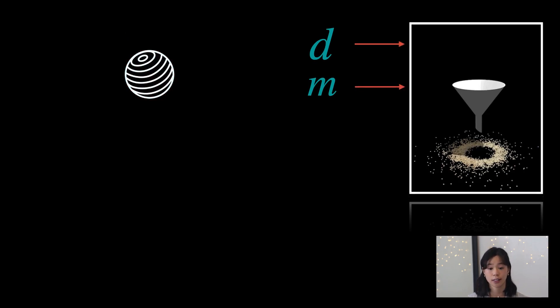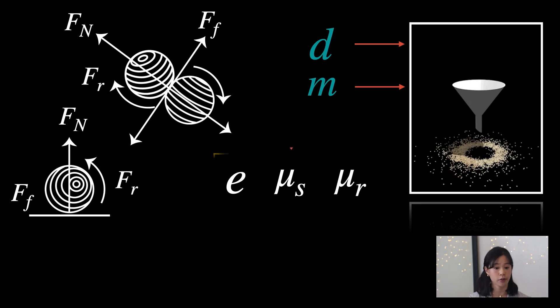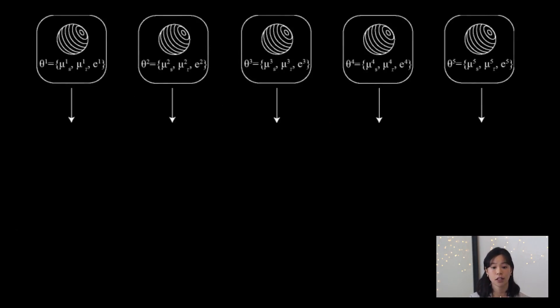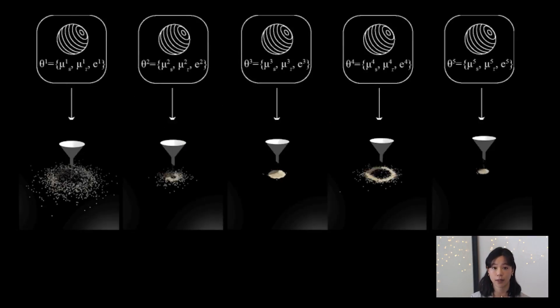The proposed framework is built upon the following simplifications and assumptions. Simulated grains are represented by rigid, cohesionless spheres of uniform size and mass, and all easily measurable features, such as diameter and mass, serve as inputs to the simulator. The parameters we chose as our variables of interest are the coefficients of restitution, sliding friction, and rolling friction. These parameters contribute to the energy dissipation of the grains upon contact and, in turn, their dynamics in steady state. Together, these three material parameters enable the simulator to generate a diversity of realistic granular behavior.